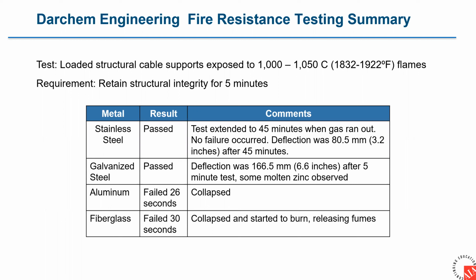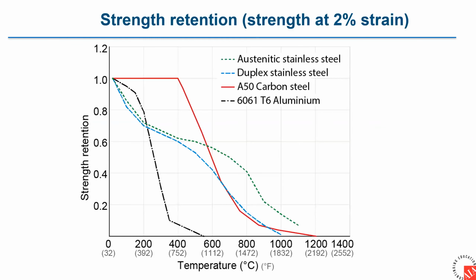The stainless steel and galvanized steel passed. The stainless steel test was a 5-minute test. The stainless steel was continued to be tested for 45 minutes until the gas ran out. Despite that added test time, its deflection was half that of the galvanized steel. So this was the starting point for research on stainless steel performance and fire, and a great deal more research has been done since.